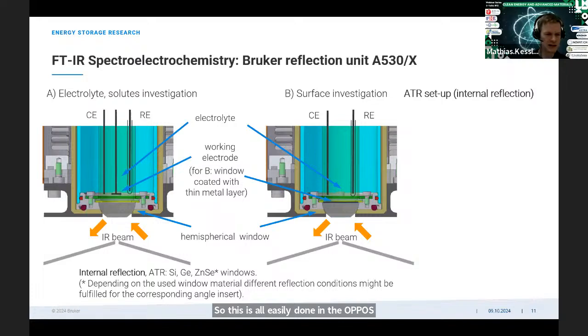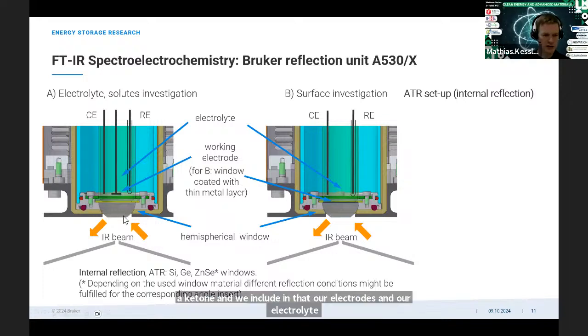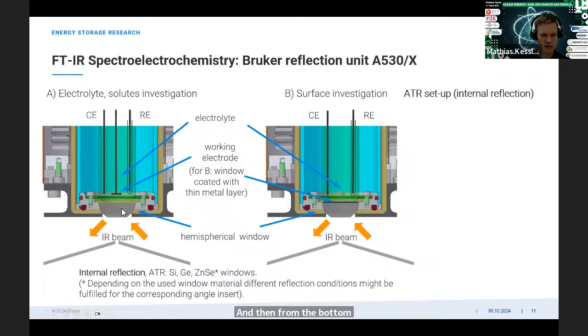How does the reflection cell look if we have a look inside? Of course, there's our cell made of glass or Teflon or polyether ether ketone, and we include in that our electrodes and our electrolyte. And then from the bottom, there's an optical window placed, which can be either silicon or germanium for ATR reactions. And then we introduce the IR beam from below to this window. It reflects internally and then goes to the detector. And so we are able to record an IR spectrum during the electrochemical reactions.